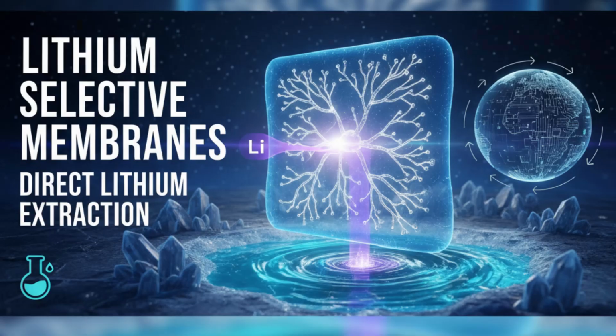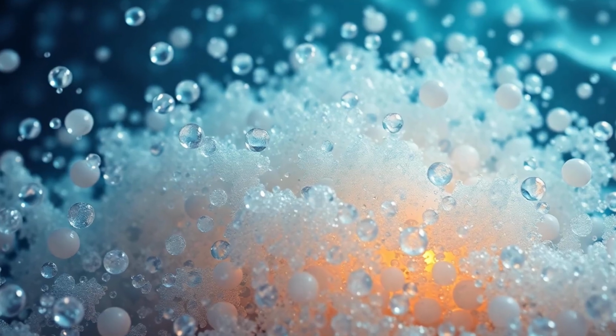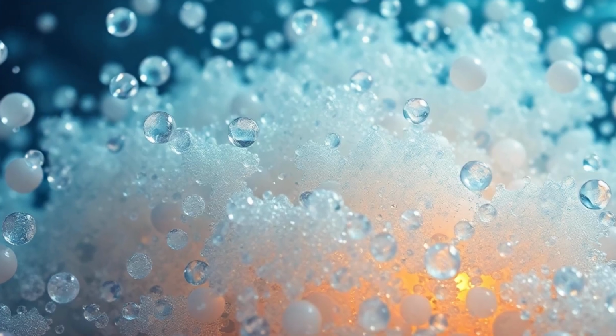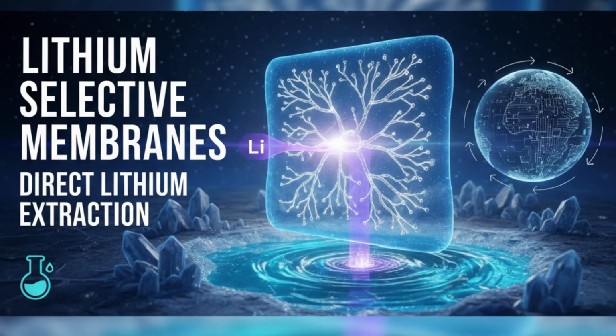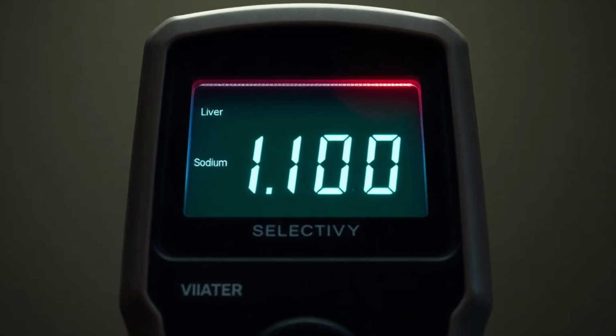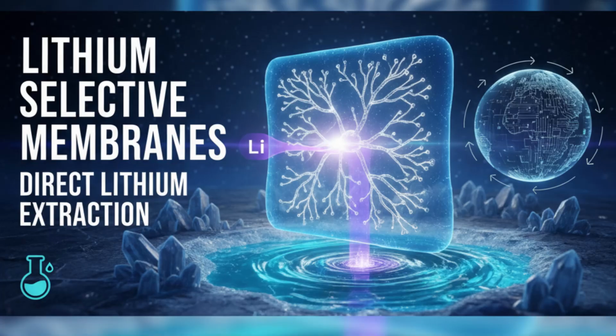And for sources like seawater, the selectivity demand is, well, it's extreme. Okay, get this. In seawater, the starting ratio of sodium to lithium is roughly 6,000 to 1. 6,000 sodium ions for every one lithium ion. Wow. Right. Now, to make extracting lithium from that viable, to keep the energy cost below about 10,000 kilowatt hours per ton of lithium, which you need for it to make economic sense, the minimum selectivity needs to be over 1,100. And that's potentially even using a two-stage process. That's the kind of precision we're talking about, just to make seawater a realistic source.